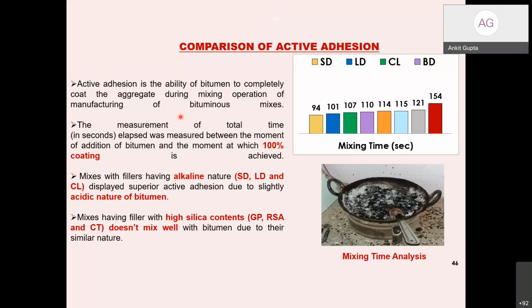So you will see that for the stone dust, the mixing time was least, and for the glass powder, the mixing time was highest. The rest of the times are comparable, but it has slight implications on carbon emissions, because you need more mixing time. That will lead to more use of fuel, or more emissions of gases.